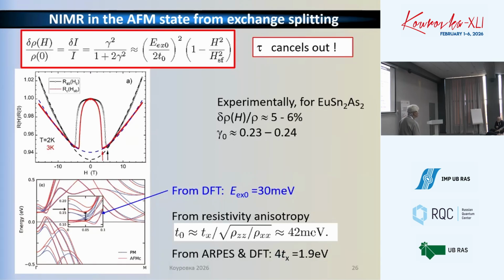What's remarkable about this effect? You see that the relative magnitude of the magnetic resistance does not depend on tau. It is produced by short-range scattering, and finally tau cancels out because it is present in the numerator and denominator. So the mechanism is universal. It is not sample dependent, it's not disorder dependent, it's universal. That's remarkable. And of course, because we consider point-like scatterers, it automatically provides the isotropy of the effect.